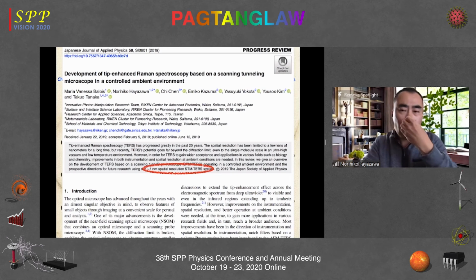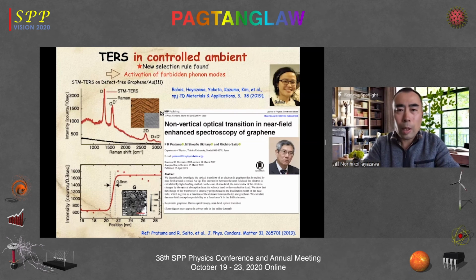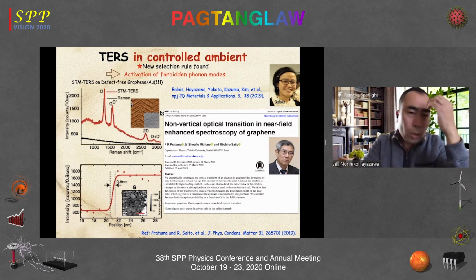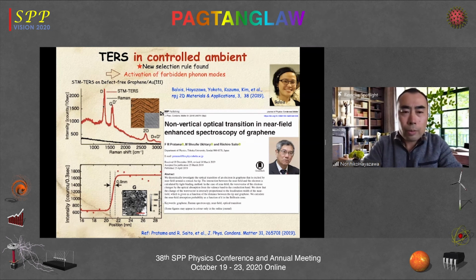Aside from the high spatial resolution by tip-enhanced Raman spectroscopy in ambient, we have found very unique physics in such nanospectroscopy. That is the new selection rule in Raman spectroscopy. For example, we observed the activation of a forbidden phonon mode from graphene. Here, the sample is defect-free graphene. And as you may know, the D-band represents the defect mode of graphene. So it means without the defect, this mode is a forbidden phonon mode. However, we observed, for example, here, a very strong D-band in our tip-enhanced Raman spectrum, although our sample is defect-free.